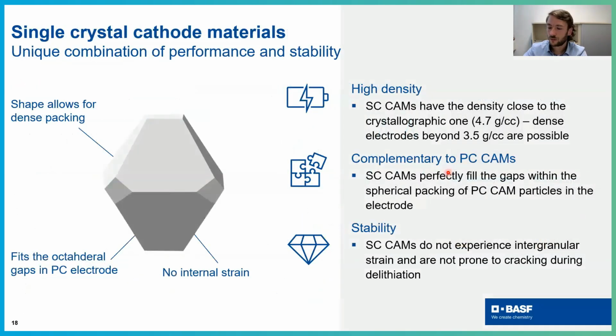Now, I would like to switch a little bit gears and speak about single crystal materials in general, and why they are interesting, and we think that they are really promising, and why it is important to develop them and also to do research on them. So first of all, these materials have a crystallographic density which is very high. It's 4.7 grams per cubic centimeter, which is much more than the typical density of polycrystalline samples, which is just 3.5.